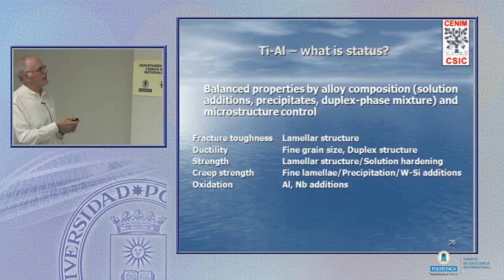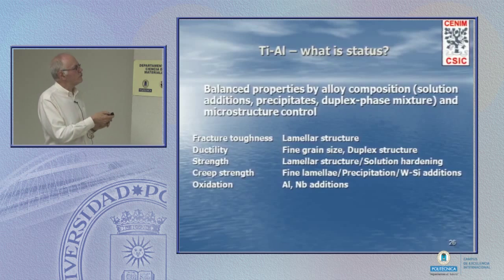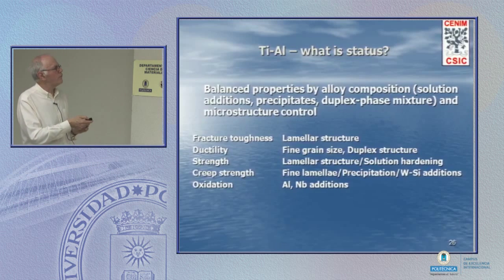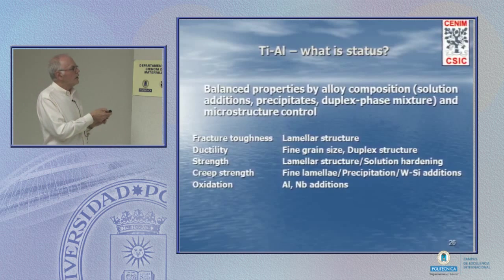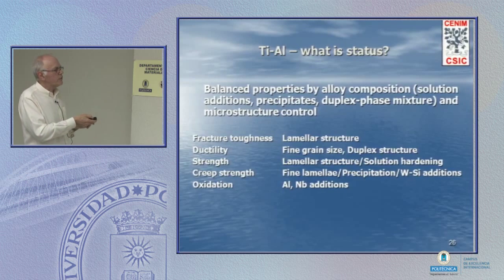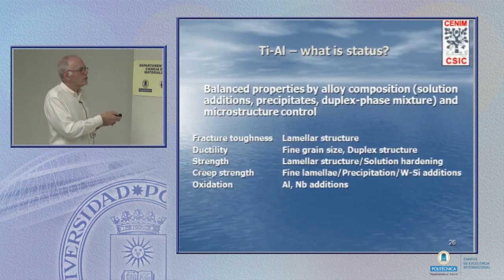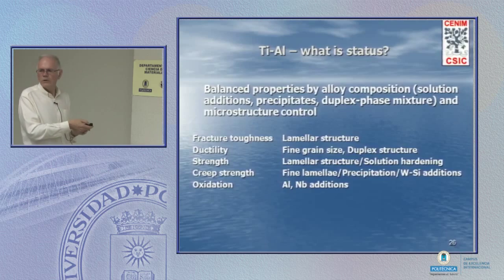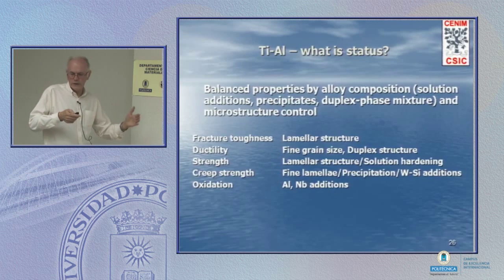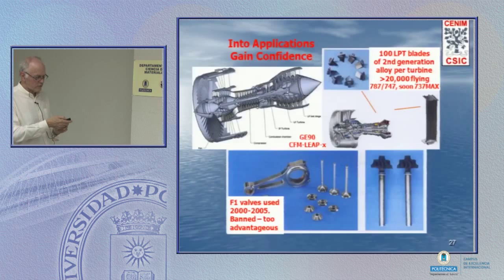Okay, so where are we today? By the selection of alloy composition, by the selection of type of phase and mixture of phase, we can balance properties. If we want high fracture toughness, we go to the lamellar structure. If we want ductility, we go to the opposing, the duplex, the globular structure. If we want strength, lamellar and solution hardening. If we want creep strength, fine lamellae and precipitates. If we want oxidation resistance, so today we essentially know within limits how to adjust. And what's the status? The status is that we're into applications.